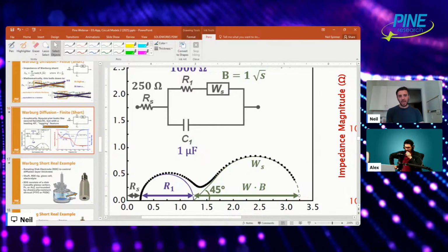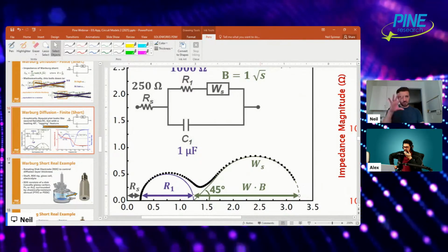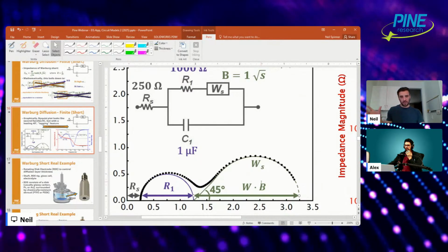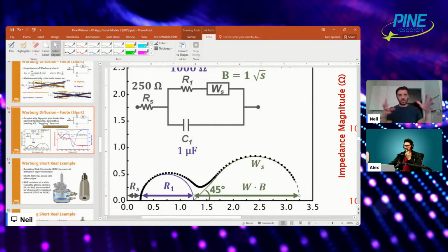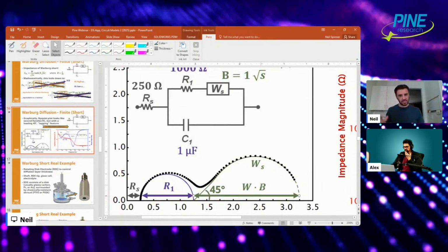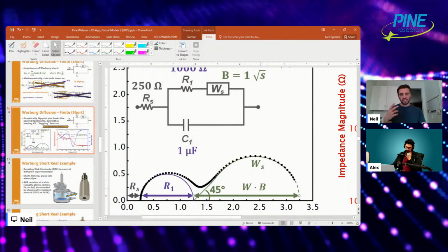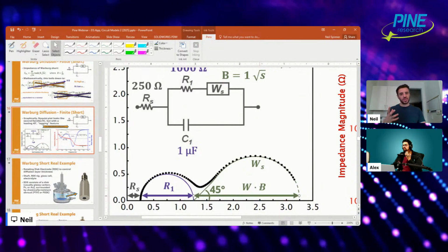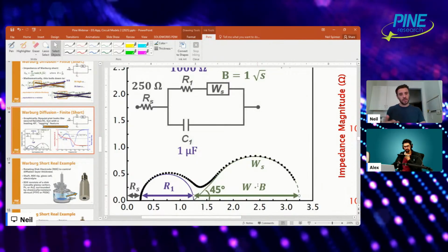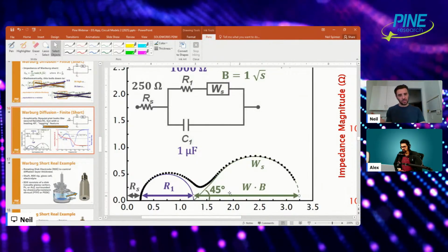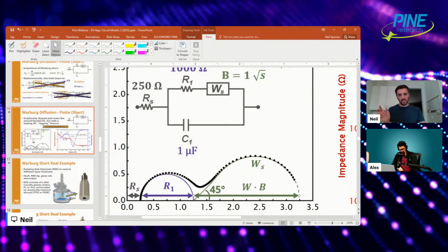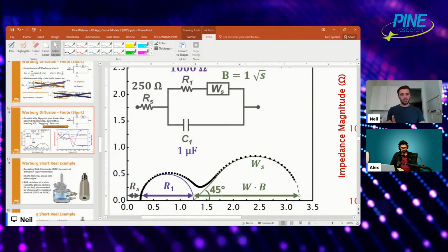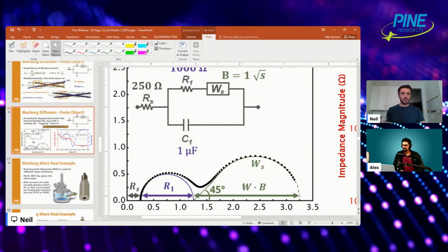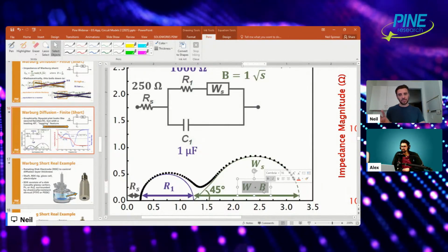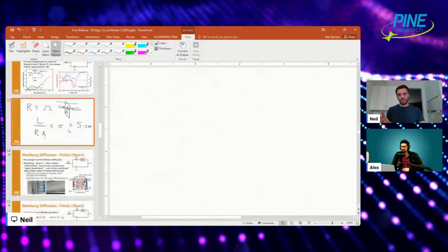And so you can imagine, even though I just told you effectively that Warburg is the impedance of diffusion, it's not like a resistance, but the Warburg short is a special case where you kind of have a situation where you have a resistance or an impedance. The width of this pseudo semicircle is dimensionally, mathematically equivalent to W times B. So it's possible that if you fit a Warburg short, you can get W and B, multiply them together, and then use that W times B as this R in your